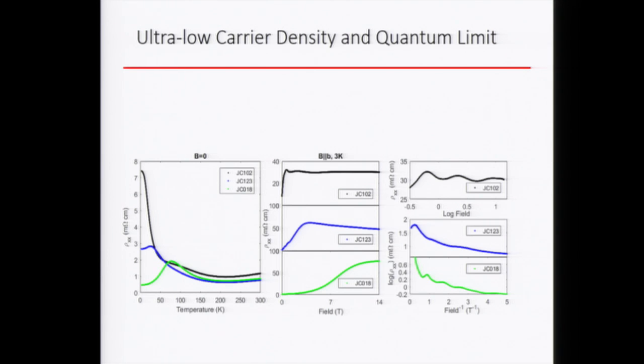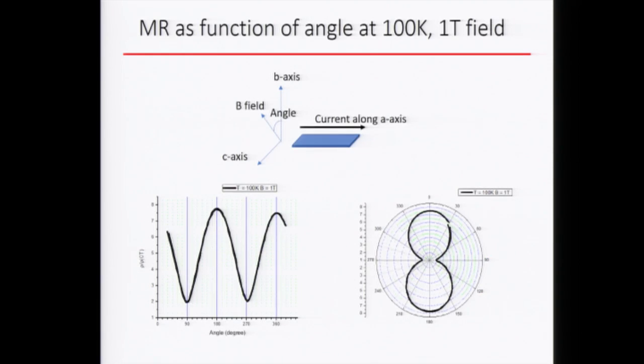So now we have an ultra low carrier density, ultra high mobility, and then we measure the angle dependence of magnetoresistance. Just to define the geometry, you're running the current along the A direction, and then you're rotating the magnetic field always perpendicular to the current, from out of plane, out of layer, to within the layers.